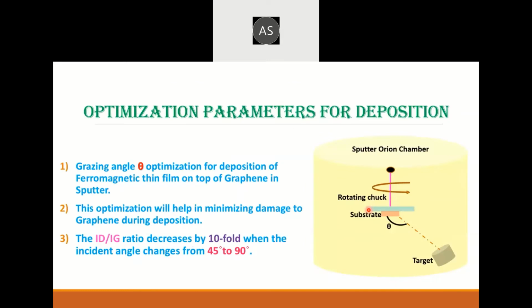After that, we found that while loading this graphene into a sputter system, it creates a lot of damage to graphene, and sometimes it also gets etched from some portions. To optimize this, we optimized the angle of deposition in our sputter system, which we call grazing angle deposition. Going for Raman again, we found that this ID by IG ratio could be decreased tenfold if we go for an angle between 45 degrees and 90 degrees. So this is how we optimized the deposition condition for ferromagnetic films on top of graphene.